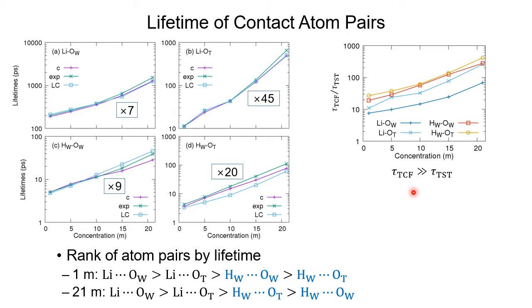However, the order of lifetimes is the same whether we use reactive flux TCF or TST. And we find that the lithium-OW has the longest lifetime at all concentrations. Therefore, this lithium-OW is the most stable both thermodynamically and kinetically, and regardless of the solvent dynamical effects. However, the gap between lithium-OW and lithium-OT is the smallest at 21 molal concentration.